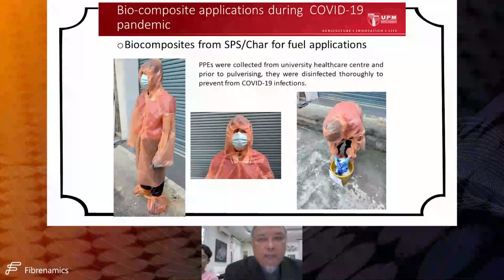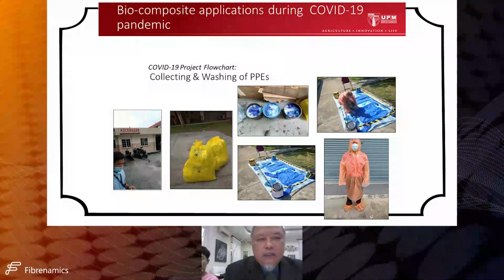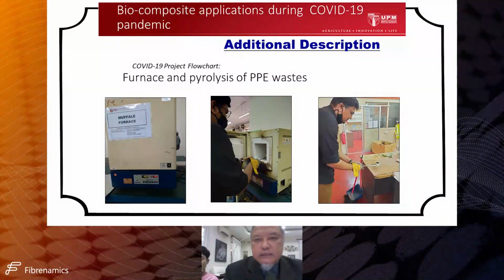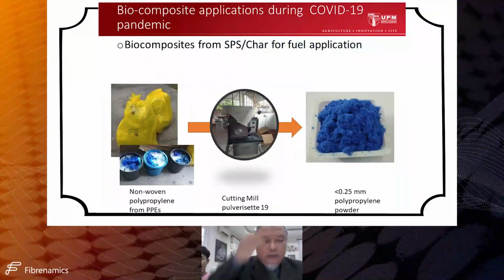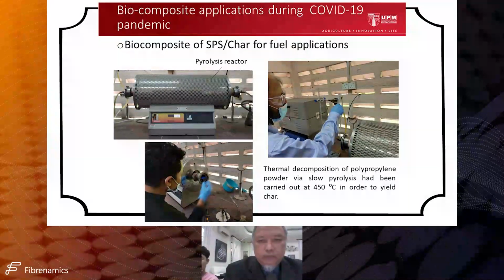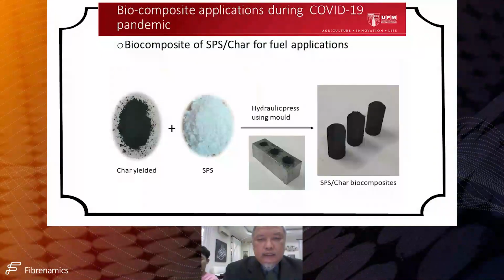And this is the gown that we wash properly so that it can be disinfected. We collect and wash the PPE and do the pyrolysis process. And see, from non-woven polypropylene PPE, we get the powder, and we do some testing and thermal decomposition of polypropylene through slow pyrolysis, and then finally we got our product. I think this is a very good work because the government is interested in that.